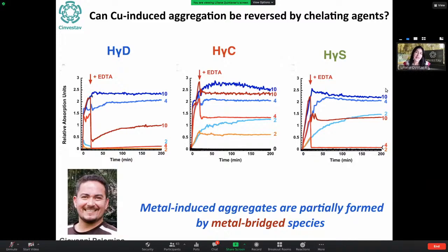turbidity again. So what we think is going on is that these big aggregates that are scattering light, some chunks of it are being held together by metal bridging. So when EDTA, we added like 100 equivalents, like we exaggerated. It's enough EDTA there to chelate all the copper there, and it's such high concentration, it will just really take it away. So you are disrupting that and you form smaller aggregates. But those smaller aggregates still have hydrophobic regions exposed, so the domain swapping mechanism that I showed you at the beginning will continue to happen even when you have disaggregated the metal bridging component. I don't know if it makes sense.